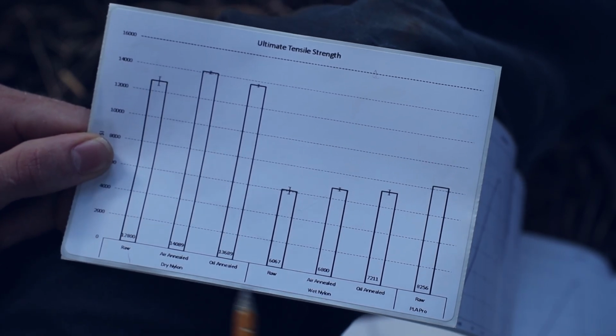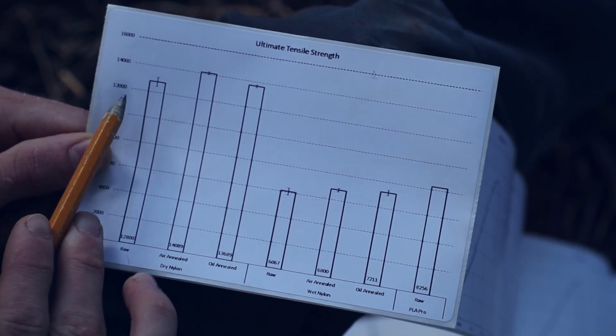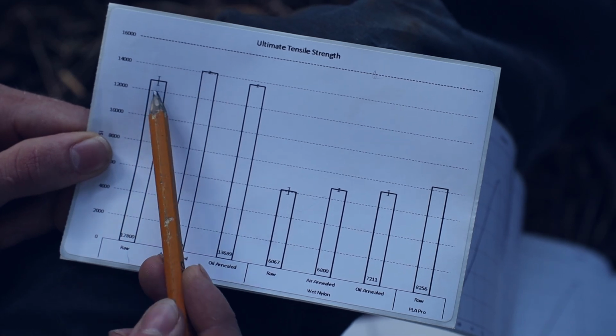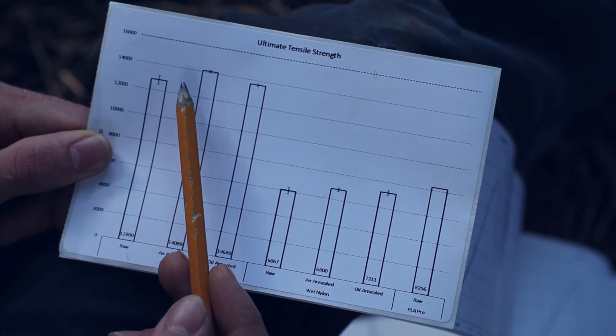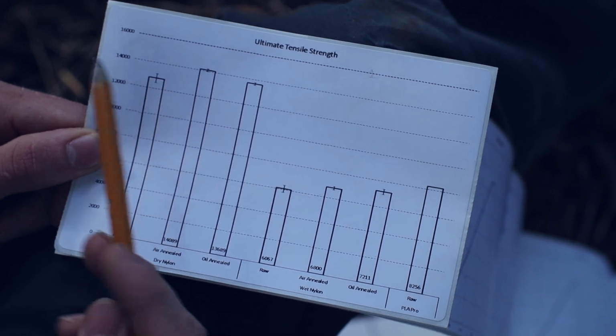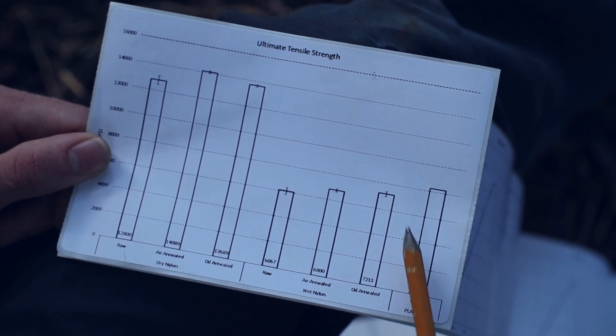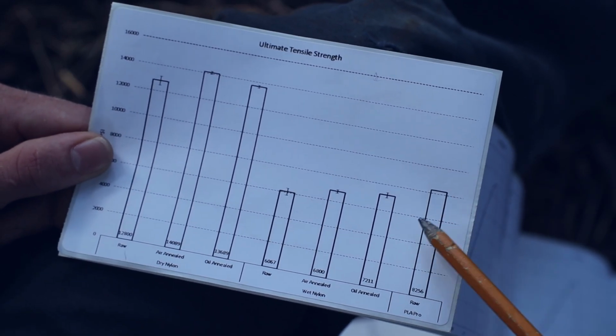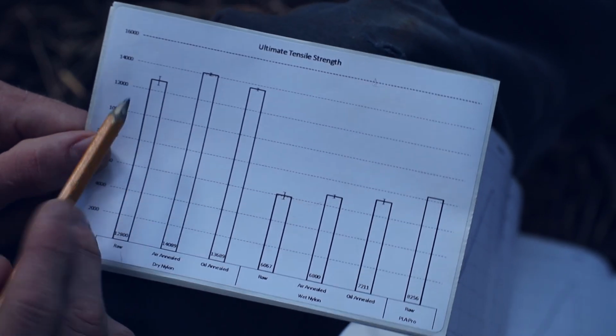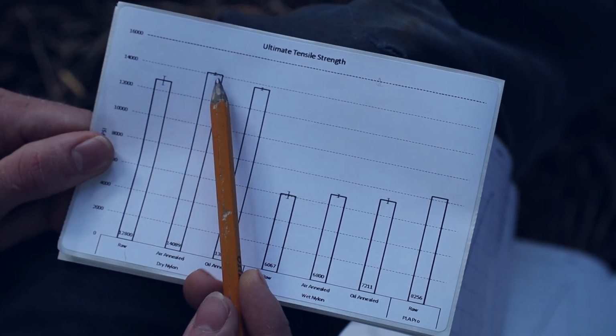Looking at this data here, I've pulled a few things out. This is the glass fiber nylon from Taulman 3D, and this is incredibly impressive tensile strength. We're looking at between 12 and 14,000 pounds per square inch, which is really, really strong. Compare that to Polymaker PLA Pro at around 8,400 way down here, and that's plenty strong for most applications.